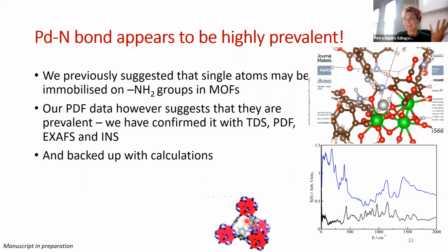From a functional group perspective, or an entropy perspective, if you wish, if you have a functional group on the linker, and you single out this corner here, then you can have two different positions because the rotation is allowed. You could have the nitrogen up here. These would be crystallographically different positions, I suppose, or it would be down here if we view it from the perspective of this node here. And we see this happen when the three nitrogen, so three amino groups, are near the corner. And I was wondering if, because we have three linkers, and we've got 4 nodes.